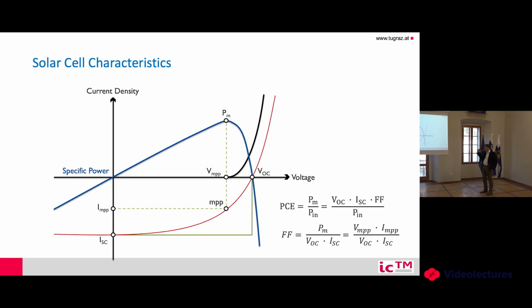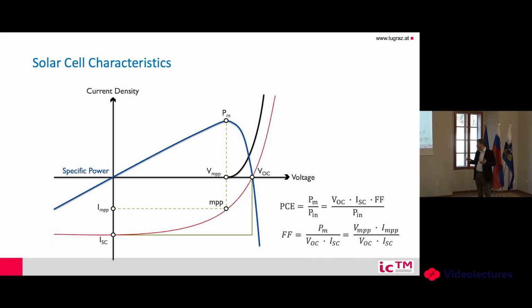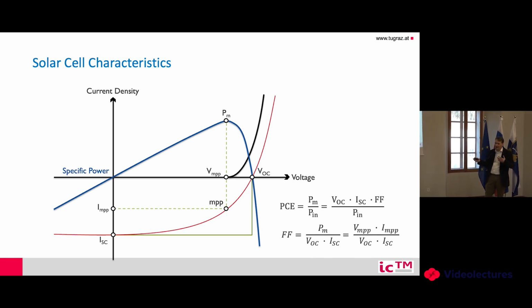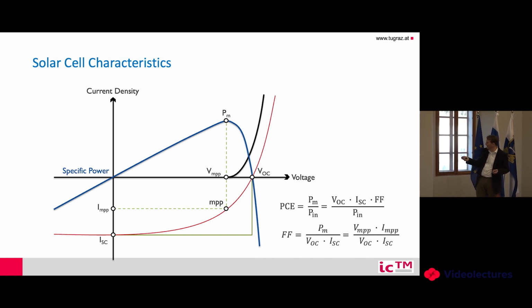But usually these are quite significant points for a solar cell, and if you have the important table of a solar cell, you always find these key figures. So actually how you define the power conversion efficiency of a solar cell. In principle, you look at the power of the light which is shone on your solar cell. So usually you work with artificial light with 1000 watt per square meter, and you look at how much power you get. So this is the electrical power which you get divided by the light power. And usually this can be explained by the voltage, the current, so the VOC, the ISC, multiplied by the fill factor, and the fill factor is this area.